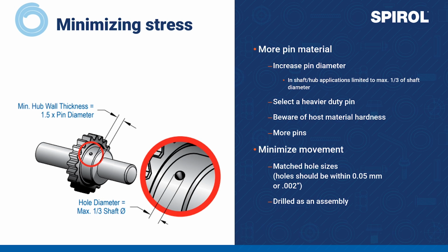Another great improvement can be made by minimizing the movement on force reversals. To accomplish this, hole sizes between mating components should be matched so that no part would have an excessive clearance that would result in shocks during force reversals. Ideally, the holes would be drilled as an assembly to have a uniform diameter, but a maximum difference of 0.05 millimeters or 0.002 of an inch should be targeted if that is not possible.